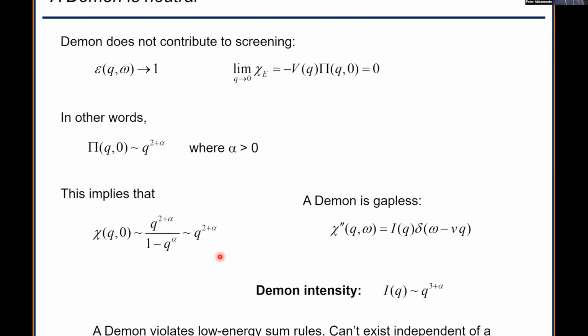If I have two baths of carriers, light ones and heavy ones, this is the way Pines thought of it. The light ones move so fast that they screen the Coulomb interaction between the heavy electrons. Those effectively become neutral, and then the collective mode of those at zero frequency is like a collective mode of neutral particles. So the consequence of that is that the demon can't live without some conventional high energy plasmon that's screening all the charge away, which is the thing that allows it to be neutral.